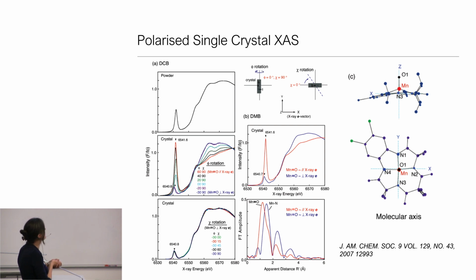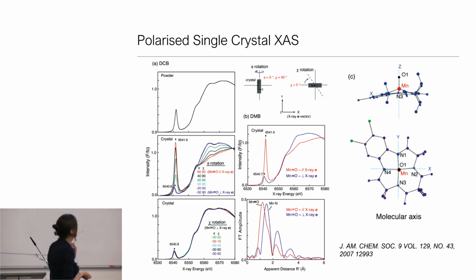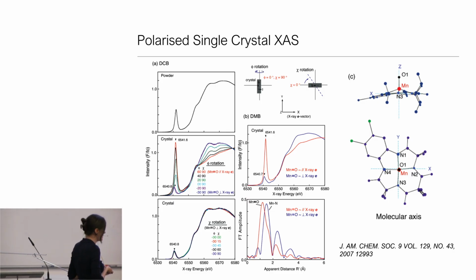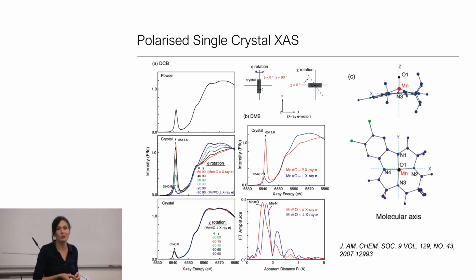And as we rotated our crystal off the manganese-oxygen bond until the point we were perpendicular to it, we had minimum intensity. And when we actually do this rotation in the plane, we only see mixing into the E set, the XZ, YZ, that are more modestly modulated. But this is just a nice way to see how that actually contributes to these pre-edge intensities. We also had polarized single crystal XAS that allowed us to separate out the axial and equatorial vectors, an experiment that one can do, but not easily.